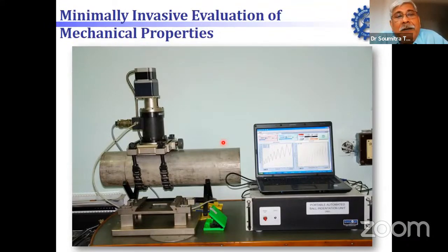Another device that we have developed is a minimally invasive device for mechanical property determination. It's called the automatic ball indentation technique, not something new, that has been there in many parts of the world, but very costly. So we developed our own version, and we developed it for our atomic energy units for looking at the degradation of mechanical properties of some of their components in service. For example, this heat exchange pipe. You can strap this device onto the component, and it makes a very small indentation of about 1 millimeter diameter and very shallow, which can actually be left behind there for certain types of components like this pipeline, because these are thick components. And you can determine how the mechanical properties have been degraded during service, if at all, and thereby understand the structural integrity concept.